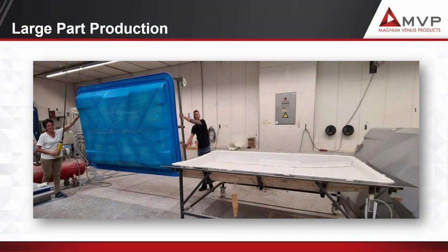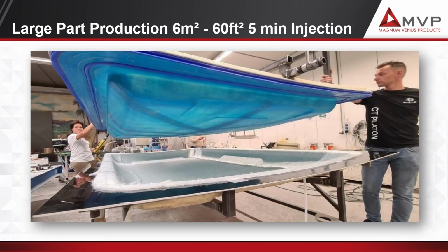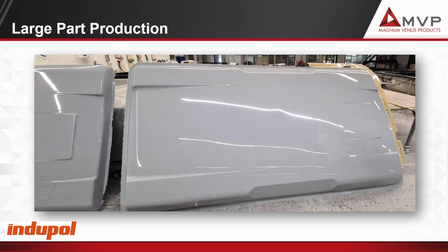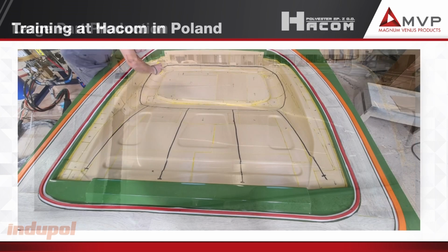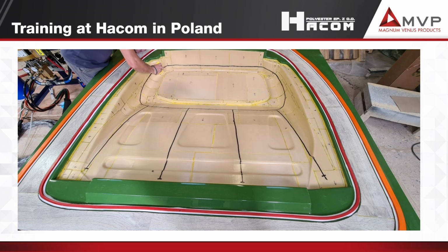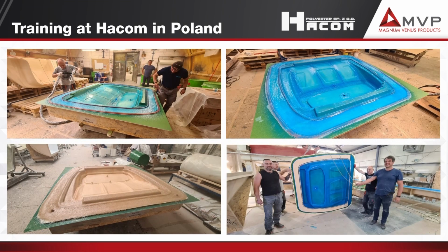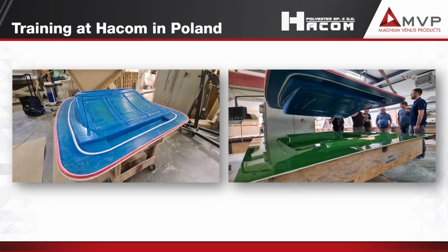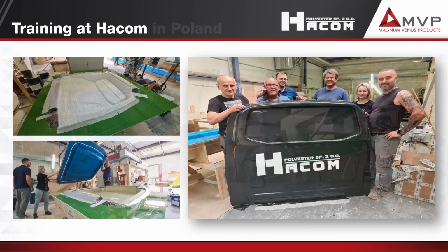So this is what we do here. We have a large part, a 6 square meter part, that we inject in less than 5 minutes. So we close the mold, inject the part, and get that. Also, another advantage of that resin is that it has no shrinkage. You can produce Class A surface finish, 0 shrinkage. So this is a customer in Poland who does the same. As you can see, silicone, composite on silicone, demold the counter mold, test the mold with the vacuum channel, close the mold, and inject the part. Same things.